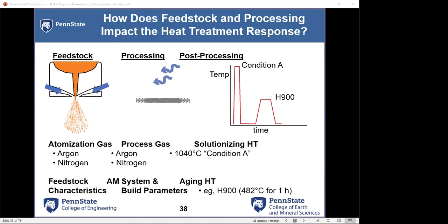the propensity to pick up oxygen, but those make their way into the materials, and the higher the oxygen, you're going to start seeing the formation temperature of the oxides increase. And in addition, the fraction of the oxides will also increase as you increase oxygen content. Ultimately, both of those factors will result in more oxides in the microstructure, and they have the potential to seriously degrade mechanical properties. So yeah, it's a good, insightful question, and I think something that people don't pay enough attention to. So I'm glad you guys are also looking at that.